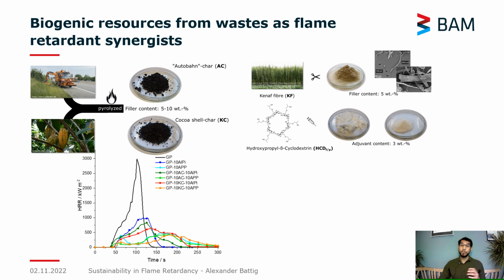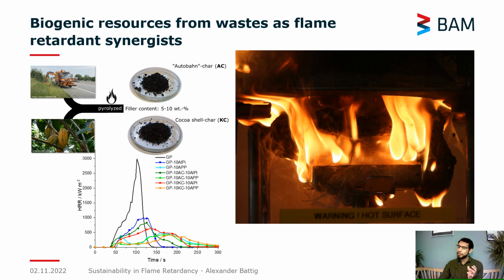flame retardants. And you'll note that the shape of the curve changes significantly, and that's because we're creating a very thick char layer. The char is actually protecting the underlying material from the fire, from the heat on the top. And it works actually really well, particularly when you use cyclodextrines. However, there is still some fine-tuning to be done. The results also show that this material can expand in volume very, very rapidly. And so it's an ongoing project, to say the least.